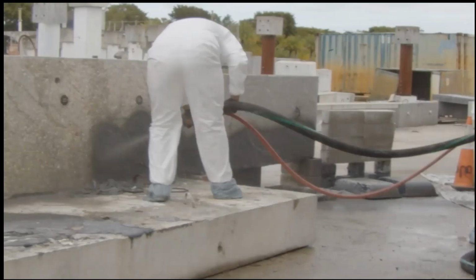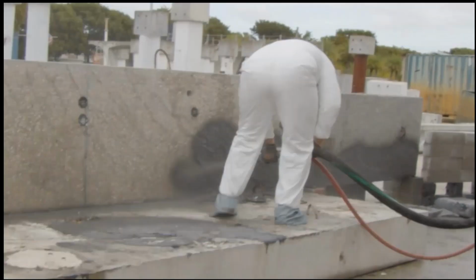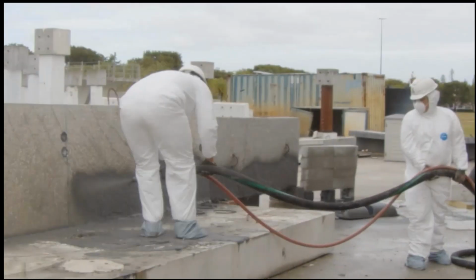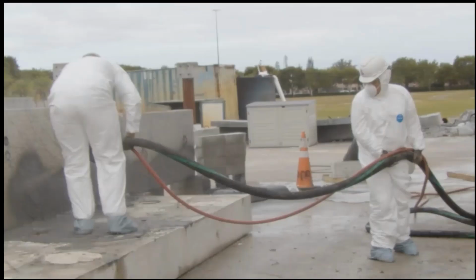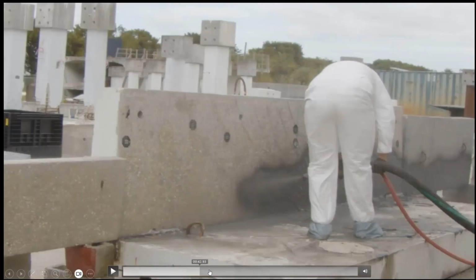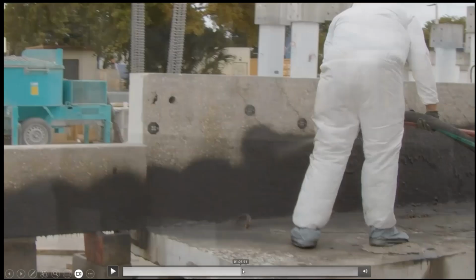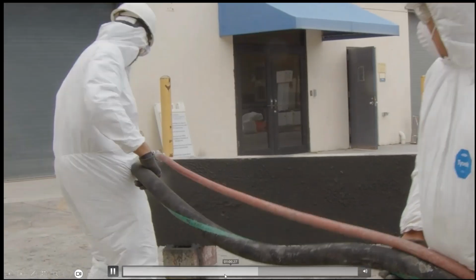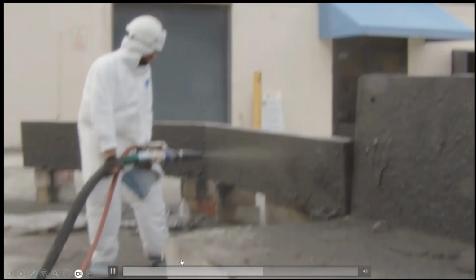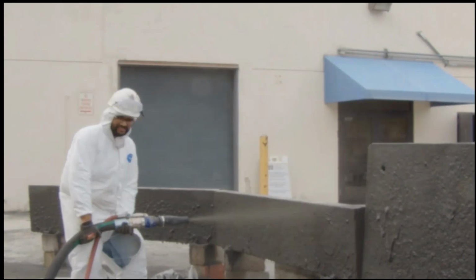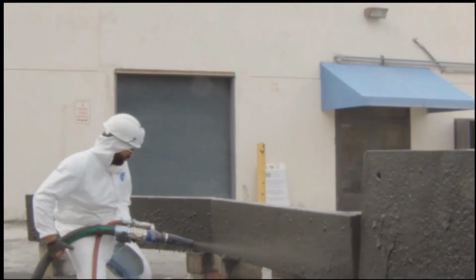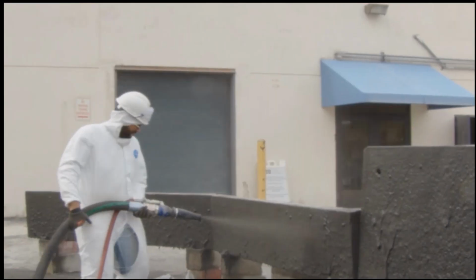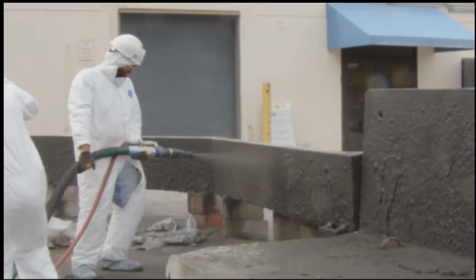Of course, the mix is important, but having the right equipment is really important because this material has lots of steel fibers, and those steel fibers basically plug the system. But you can see here that you can apply several layers. Like, for example, here you see that we are applying additional layers. But you have to let the first layer dry up a little bit before you apply the next layer. If you use the right mix, the elastic rebound is really minimized.